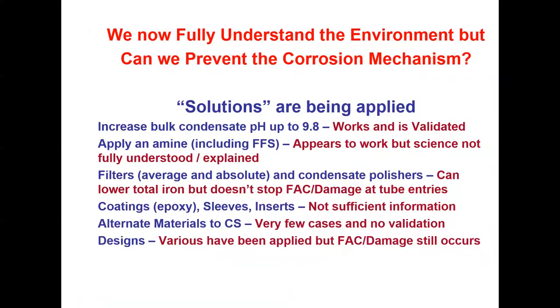So we understand the environment, but can we prevent the corrosion mechanism from taking place? We find from these ACC meetings and from inspections and assessments that solutions are being applied. Probably the most important one at the moment is increasing the bulk condensate pH, which can be up to 9.8. I'll show you the curve in a minute. We know that this works and is validated.